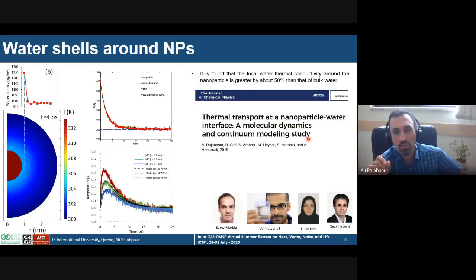About our ongoing projects in these applications, I would like to talk about the water shells around the nanoparticle. As we know, a shell of water is formed around the particle in water, which has different properties from the bulk water. This layer, because of the solid-liquid interaction, has higher thermal conductivity, higher density, and also higher viscosity. Also, this layer is very thin. It can be important at the nanoscale. This project is being implemented in collaboration with Samy Merabia from Lyon and two of my postdoctoral researchers, Fatime and Reza.